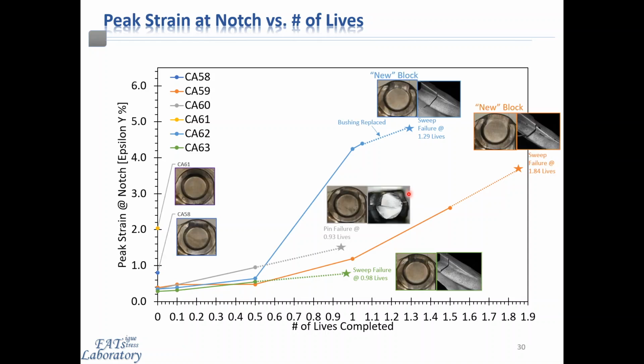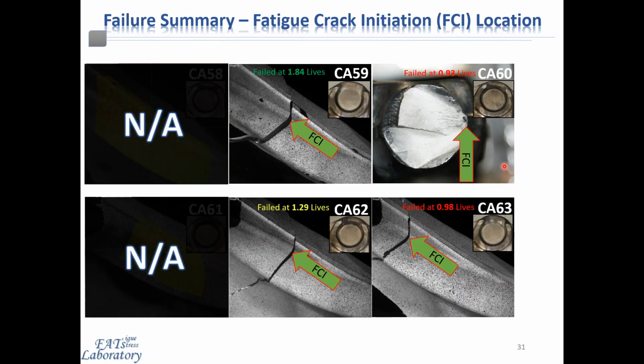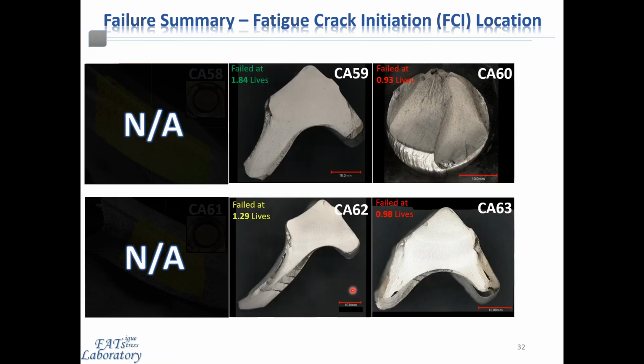Overlaying some of the images of the forging and the crack morphology provides more evidence as to how the strain evolves as fatigue damage is accumulated and then eventual failure occurs at the end of each of these response curves. Comparing the nature of the final failure for 4 of 6 components, we can observe that 3 of the 4 had similar cracks in the location which was previously discussed. So that's these 3 here. And for the purposes of this presentation, I'll compare and contrast these failures to trace the microstructural origin.